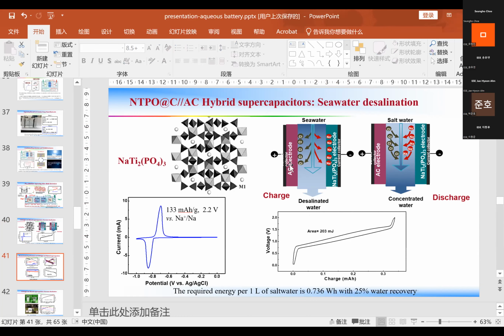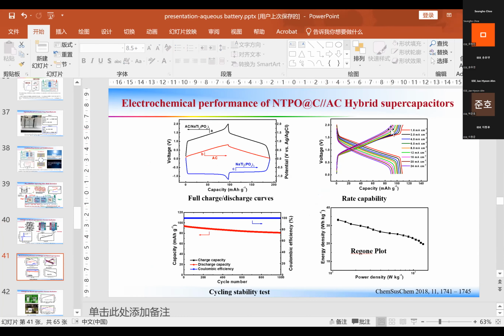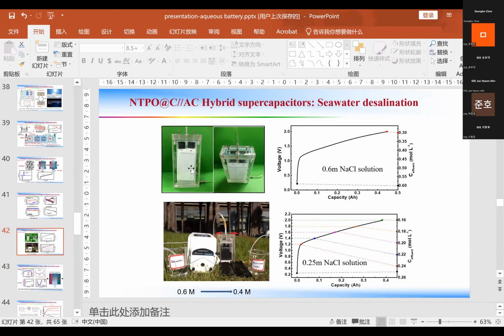This shows the electrical performance of this hybrid supercapacitor. It has good power and also good cycling stability. And then we just use these cells. The primary concentration of sodium chloride is 0.6 mole, and after we charge it to 1.6 volts, the electrolyte concentration will reduce to 0.3 mole. So this is desalination.